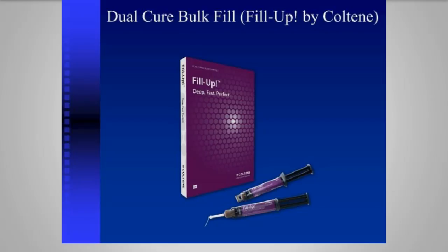And it's interesting, by Clinicians Report, a recent survey of 786 dentists indicated that 49% see a need for dual cure restorative resin for class 1s and class 2s, and in areas where the dual cure would be most desirable, or the deep preparations. Most bulk fills are highly light cured, but then you're going to have a highly translucent material on a lot of them, especially the flowables, because you can't have a lot of opaque particles to mimic tooth structure because the light's got to get down deep into the material itself. So Fill-Up is a dual cure medium viscosity material.